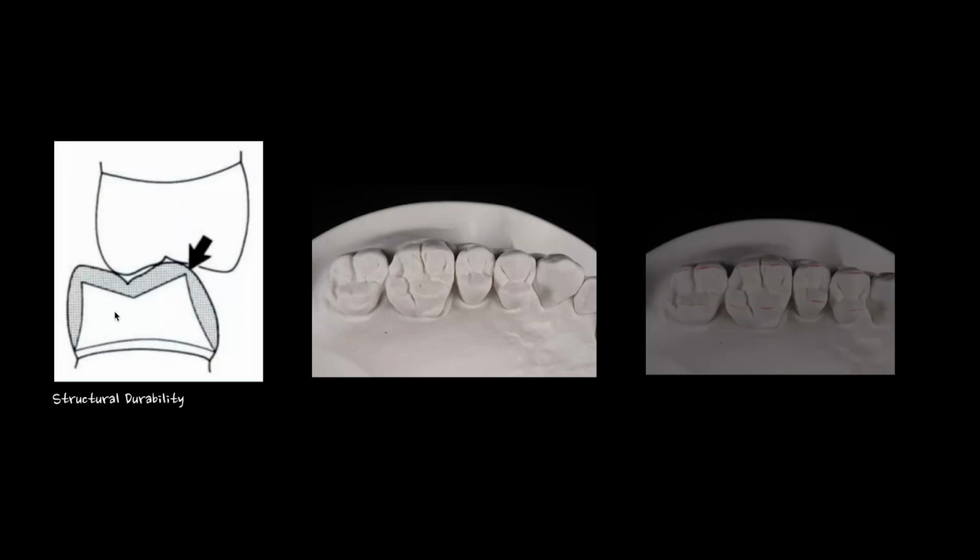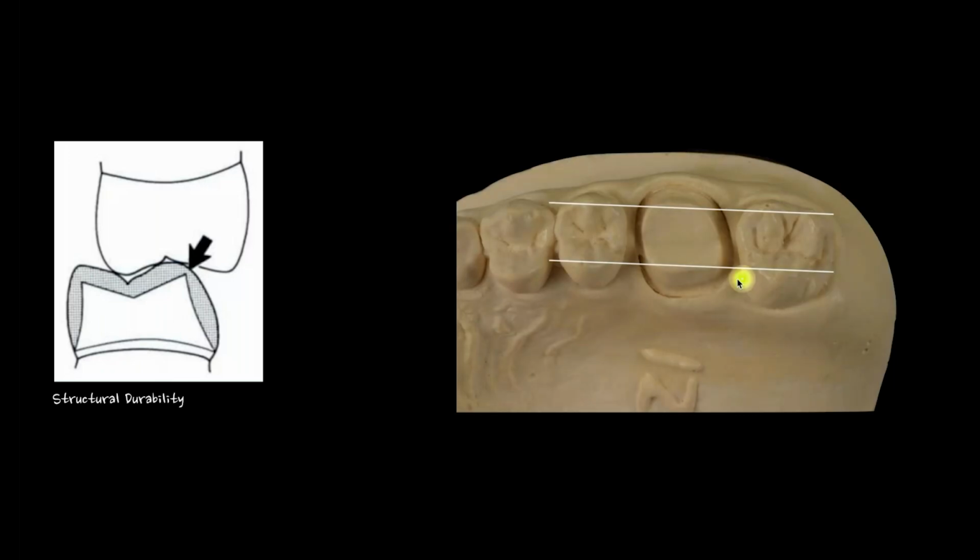So I want to always help the doctors realize that when you're prepping your posterior teeth, you're looking at the occlusal table more than you're looking at the angulation of the tooth. It's more about moving the angulation to fit the need of the occlusal table, not the other way around. So what I see a lot of times is that the occlusal table is not reduced enough, or that third plane is not rolled in enough. And that presents a big challenge for us, especially in the monolithic world. So for those of you who are only doing digital impressions and only doing monolithic molars, and that's very common today, this is the area where you're going to find fracture almost all the time.